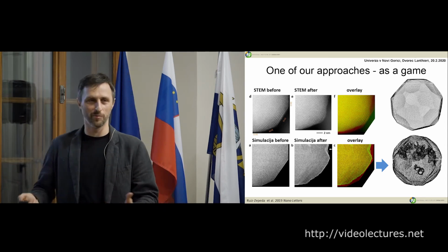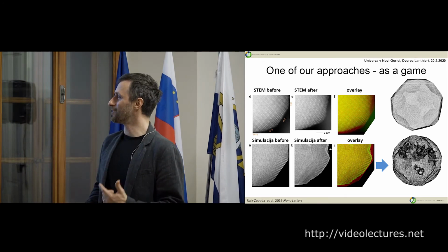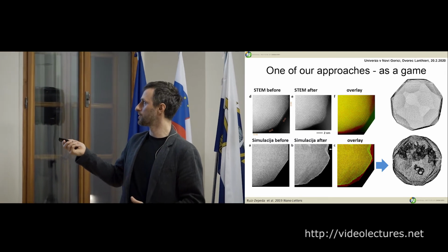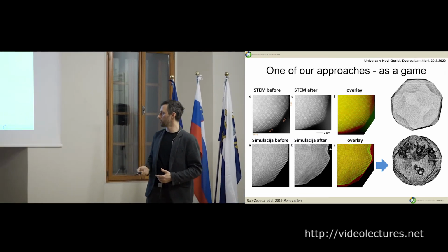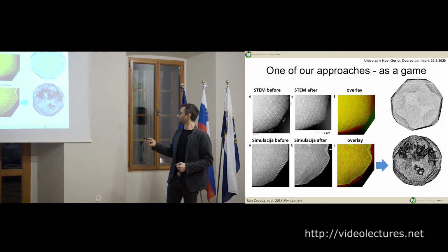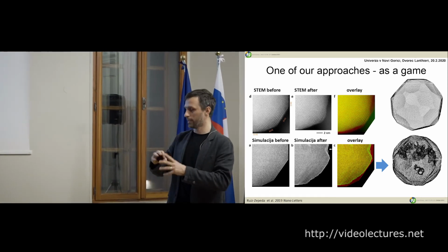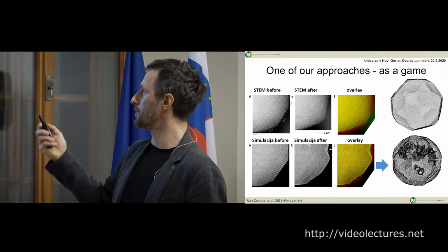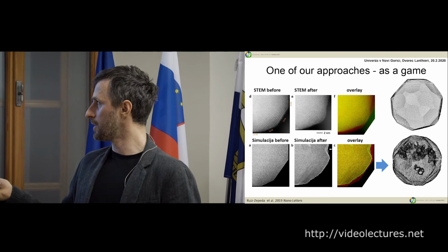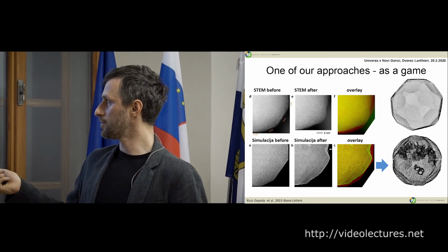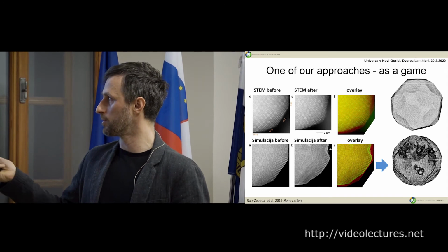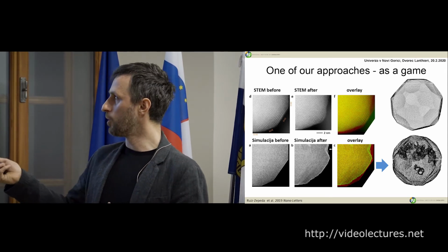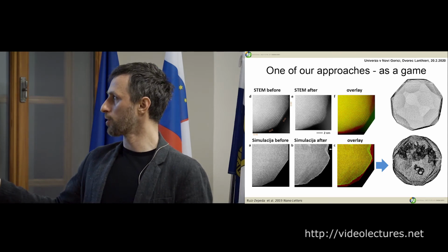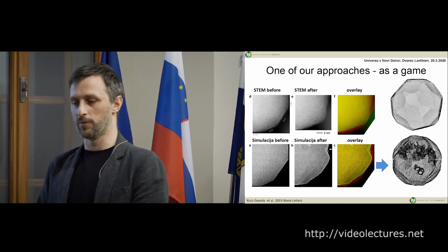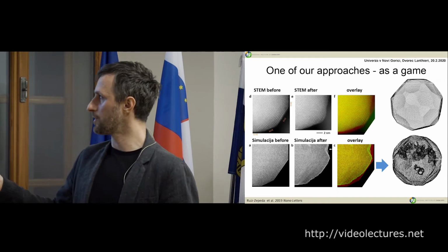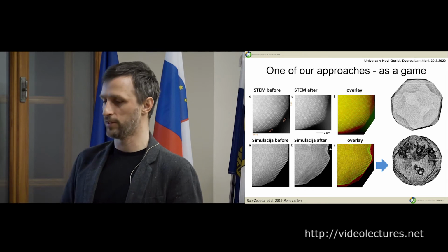So it's kind of obvious now, but it was not in the beginning. So again, Andras took these snapshots and made the simulation, and then because he made the Monte Carlo, he has the positions of all the atoms. He can also make these nice 3D movies. But what we figured out is that he could only get this etching from the sides if he puts more copper on the sides. So we could only simulate this process if we put more copper on these facets. So this was kind of a backward information. Okay, these facets are more rich in copper, and the 111 facet is richer in platinum.